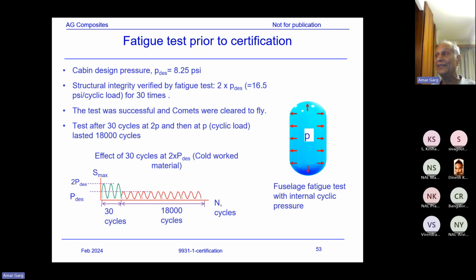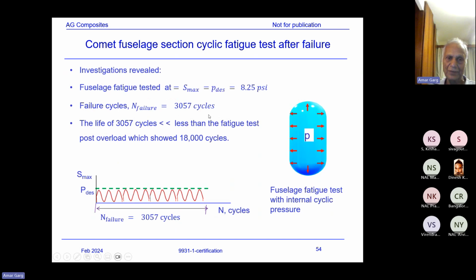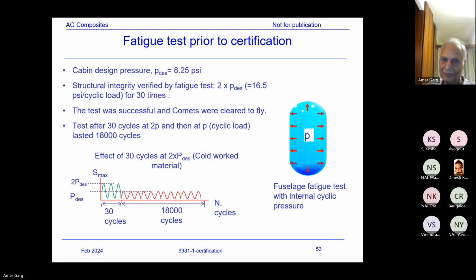But what happened when they tested later on? This slide I'll show before I go back to the previous one. After the failure, when they were doing the failure investigation, they tested the fuselage again, for the design pressure fatigue cycle. And to their surprise, they found the fuselage failed at only 3057 cycles. About 3000 cycles, the fuselage failed. But when the overloaded fuselage was tested, that is, after double the pressure, 16.5 psi for 30 cycles, and then tested at the design pressure, it lasted 18,000 cycles. Now, why is it so?